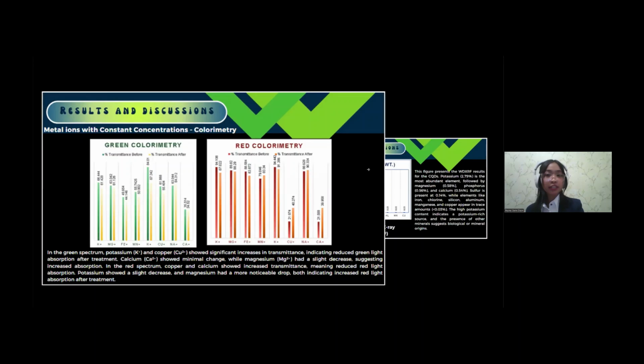This experimentation lets me analyze how the different heavy metals react to different light, which was used for my quantitative data using the NeuLog logger sensors colorimetry analysis. The first figure shows how the CQDs affect green light absorption. Potassium lets a lot more green light through after treatment, meaning it absorbs less. Copper lets more green light pass, but calcium barely changes. And magnesium actually absorbs a little more green light after treatment.